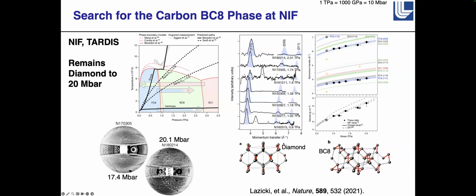We also wanted to look for the BC8 phase of carbon, which has a tetrahedral crystal structure. So you've got perfect sp3 bonding in diamond, which makes it very strong and very stiff. The BC8 phase is not nearly as symmetric, but it also has very nearly tetrahedral bonding. And this transition, all the theorists predicted, should happen at about a terapascal, about 10 megabars. We compressed up to 20 megabars and we still saw diamond. So that was frustrating. I really wanted to see this, but we were unsuccessful back in 2018, 2019. And Amy Lazicki published, the first author on this paper, in 2021. Currently we have more discovery science campaigns where we're trying different ways to get up to this phase, and we're optimistic that we will see this phase within the next few years.